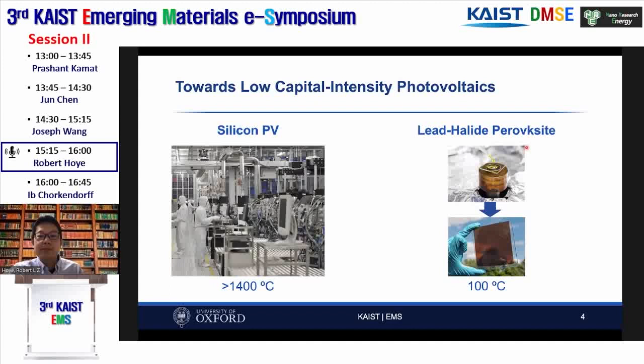Now contrast that to the more recent material, lead halide perovskites. This can be fabricated in much dirtier environments using much simpler equipment, for example, by solution processing. The temperature required to process these materials is a lot lower, so the thermal budget involved is a lot lower, and perovskite photovoltaics can have a much lower CO2 footprint. The energy payback time for perovskite PV is predicted to be just a couple of months, whereas for silicon PV it is a couple of years. This is quite a big difference, and perovskite PV have a lot of potential for making very cost-effective photovoltaics that may be scalable more quickly.